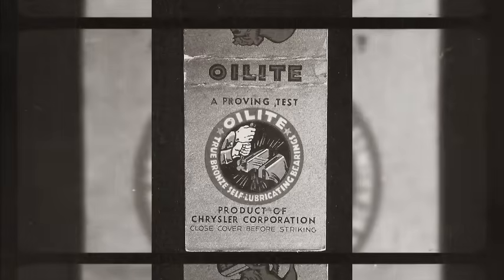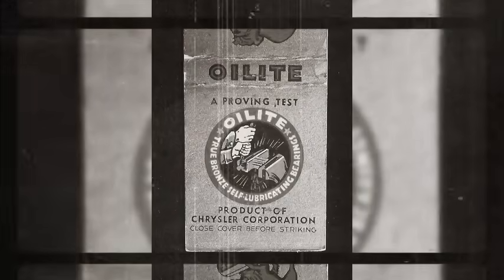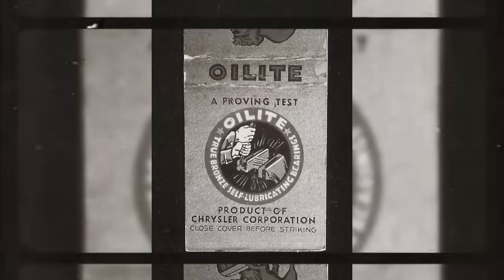The result: bearings with approximately 25 to 30% porosity by volume, filled completely with oil. The pores, microscopic interconnected channels, held oil through capillary action, but released it when heat and friction reduced oil viscosity and expanded the metal slightly.